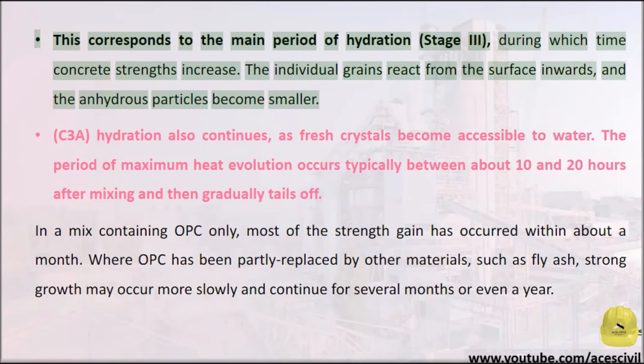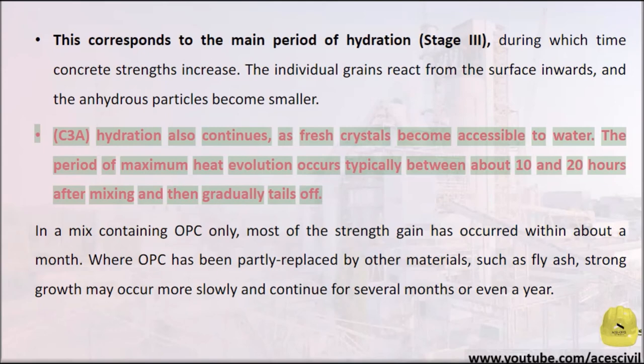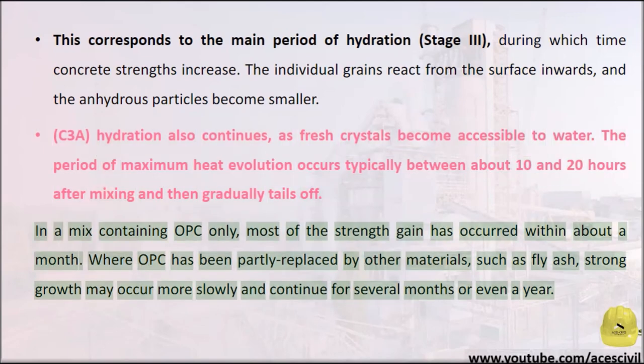This corresponds to the main period of hydration, Stage 3, during which time concrete strengths increase. The individual grains react from the surface inwards, and the anhydrous particles become smaller. C3A hydration also continues as fresh crystals become accessible to water. The period of maximum heat evolution occurs typically between about 10 and 20 hours after mixing and then gradually tails off. In a mix containing OPC only, most of the strength gain has occurred within about a month. Where OPC has been partly replaced by other materials such as fly ash, strength growth may occur more slowly and continue for several months.